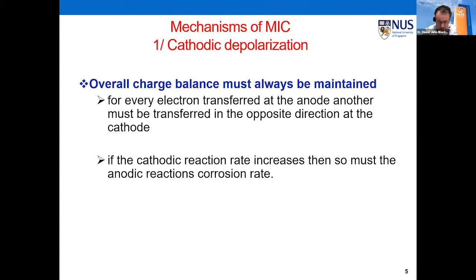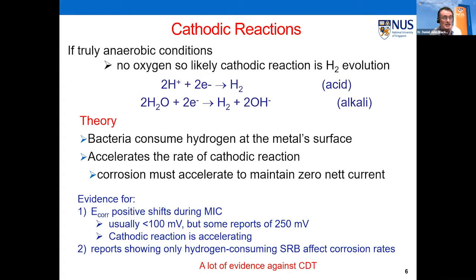So this cathodic depolarization, which has been around for a long time, is based on the basic idea of corrosion, right? That your cathodic and anodic reactions have to be at the same rate. For every electron transferred at the anode, another must be transferred in the opposite direction at the cathode. So if you increase the cathodic reaction rate, you'll increase the corrosion rate. So that's the basic concept behind the cathodic depolarization theory. And if it's truly anaerobic, then the cathodic reaction is supposed to be hydrogen evolution. So the bacteria consume the hydrogen at the metal surface, that accelerates the cathodic reaction, and corrosion must accelerate to maintain zero net current. There is some evidence for that.